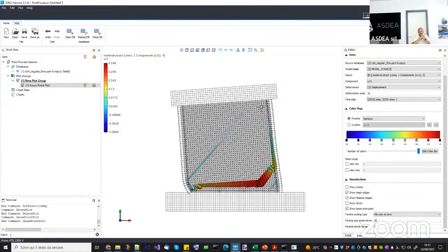One thing is that whenever you do analysis of strain softening materials, you have to pay attention to the size of the mesh, as Professor said, but also to the orientation. It's true that we do fracture energy regularization, either in the beam truss model or in the continuum model, but the only thing that you regularize is the amount of dissipated energy. The problem is that the finer the mesh, the more uniform is the material that you are trying to simulate, okay? So the crack will develop much faster. In this case, the first crack that appears, which in the coarse mesh was stopping and allowing the diagonal crack to form, is now forming much faster. And it promotes a sliding at the base rather than a diagonal crack.